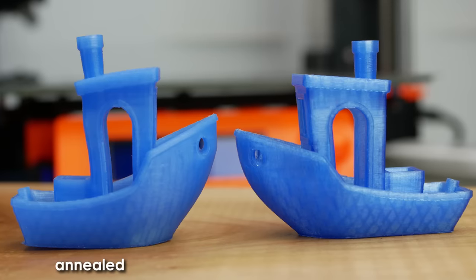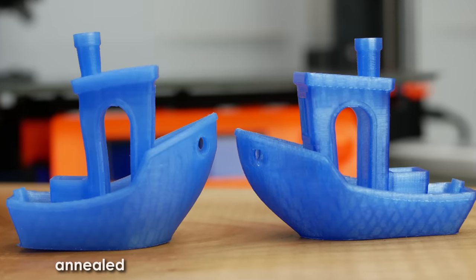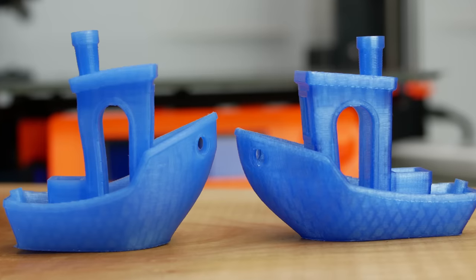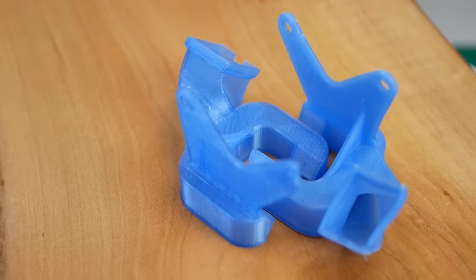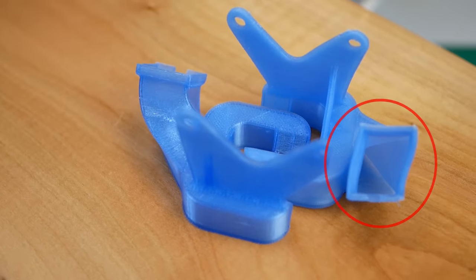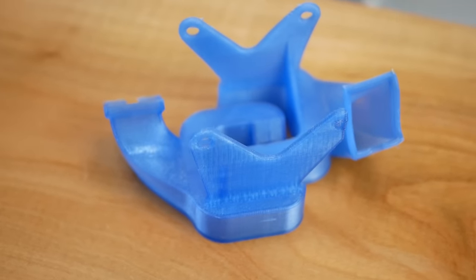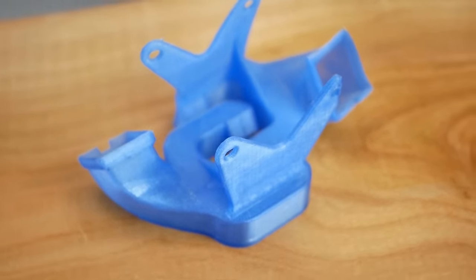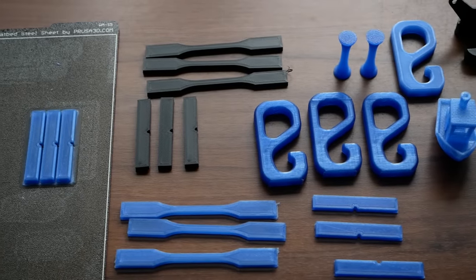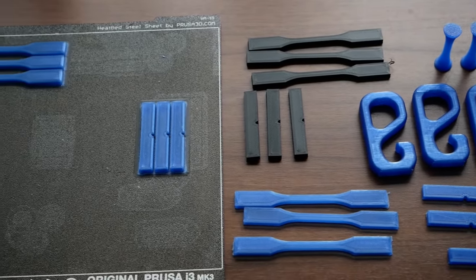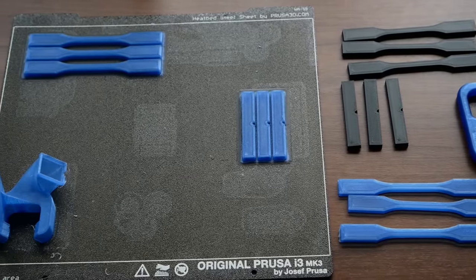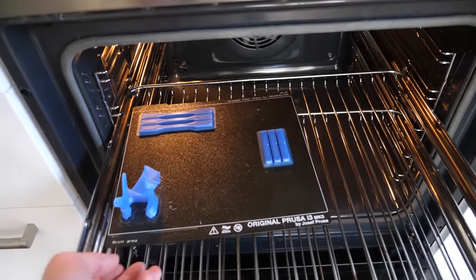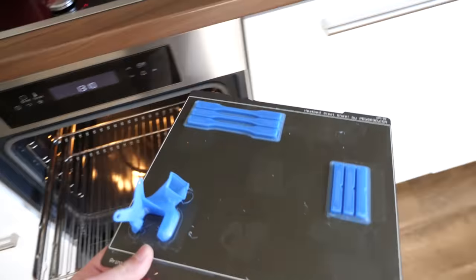Unfortunately, the amount of deformation is not always the same and can rarely be compensated by just scaling the parts. This is particularly obvious if we take a look at the fan shroud that just wobbed all over the place. There are a couple of ways how you can minimize that effect. One way that I often use due to my removable print beds is that I put the parts into the oven still attached to the base with all of the supports and that greatly reduces a lot of warping and keep at least the base straight.